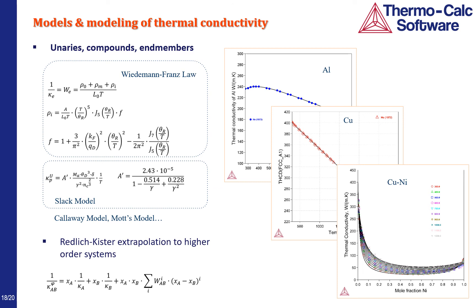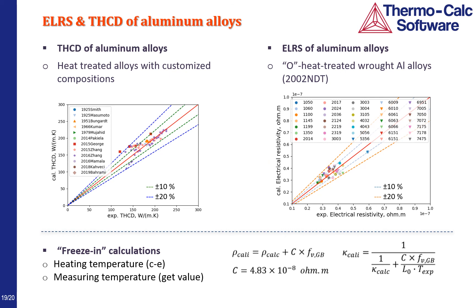The modeling of thermal conductivity is done together with that of electrical resistivity, since they are related: electronic thermal conductivity can be derived from electrical resistivity via the Wiedemann-Franz law. The lattice thermal conductivity may be approximated with the Callaway model or the Slack model. The plots shown are for pure aluminum and pure copper. The extrapolation to higher-order systems also relies on the Redlich-Kister expression, but it applies to the resistivity rather than conductivity. For multi-component aluminum alloys, most data can be accounted for within an uncertainty of 20%, and many within 10%. Since properties rely on phase constitution, we should use the so-called freeze-in technique: calculate phase equilibrium at the solution treatment temperature, then change the temperature to the measurement temperature and retrieve the results without recomputing phase equilibrium.